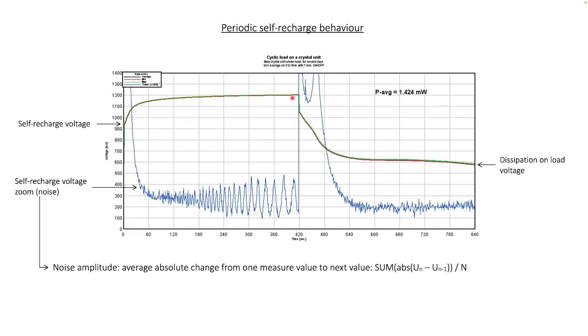What is difficult to see here is that the minimum and maximum run of the voltage is very close to the average. Basically, the curves are overlaid on it. This means that the behavior is very reproducible and that no variations can be really detected from that self-charging behavior.